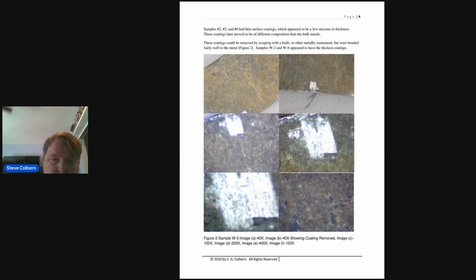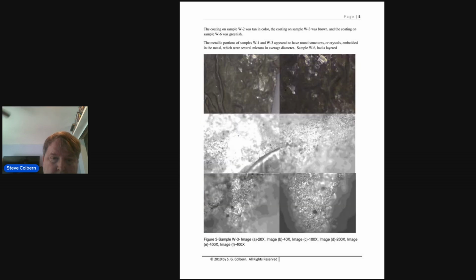Next page. And here's sample W3. This one had more of a bright appearance in many areas. And also you can see some microstructures that were smaller than on the first sample. It just looks very strange compared to most aluminum pieces I've seen before. But it's very interesting that the strength of these materials was not very impressive compared to some of the alien materials or possible alien materials I've seen before.